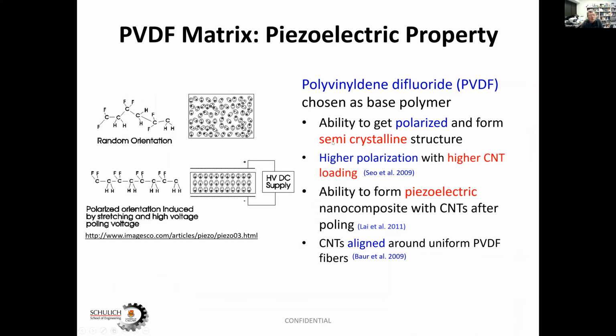As I mentioned before, PVDF is a unique polymer. Regularly it's a random orientation, the polarity is all over, it's not quite aligned. When you apply high voltage, these fluoride chains get aligned and you exhibit piezoelectric properties. Okay? So in our case, we apply corona charge of about 15 kilovolts.